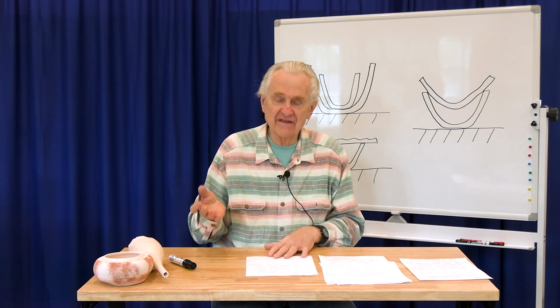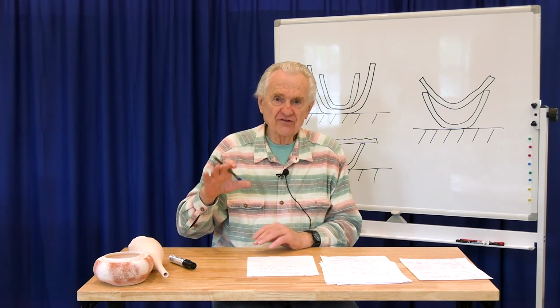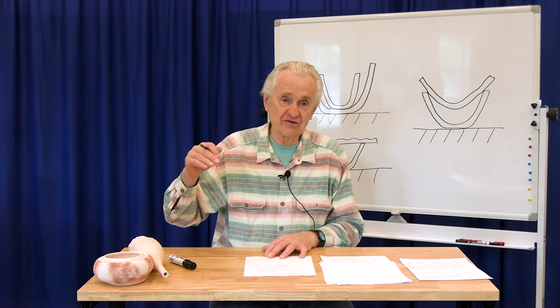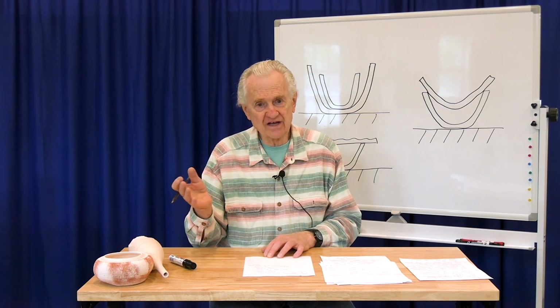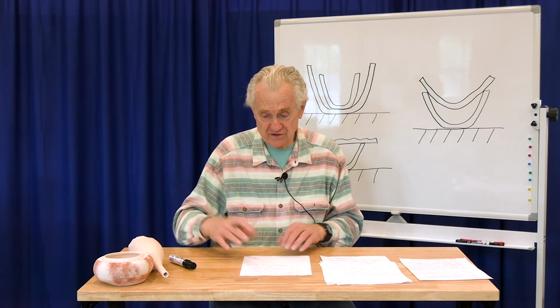And then finally, late in the afternoon, I'll turn the kiln up to high. By that point, most of the water has been removed from the clay. At this point, I'm going to a higher temperature to strengthen the clay. So I'll turn the kiln up to high, I'll close the top peep, and typically I found it only takes an hour or 2 hours on high to reach the final temperature.